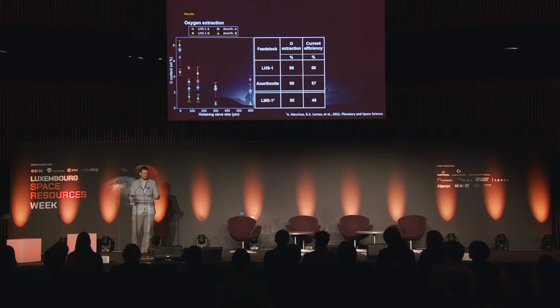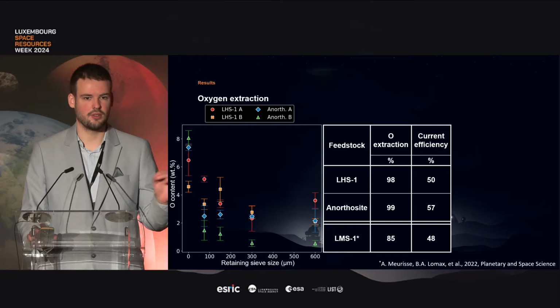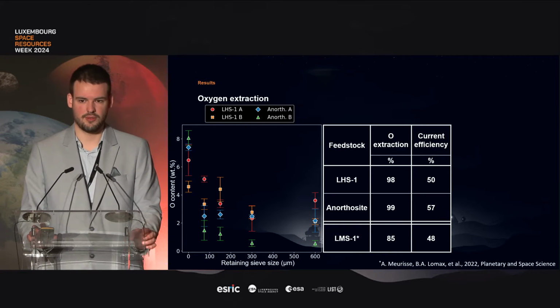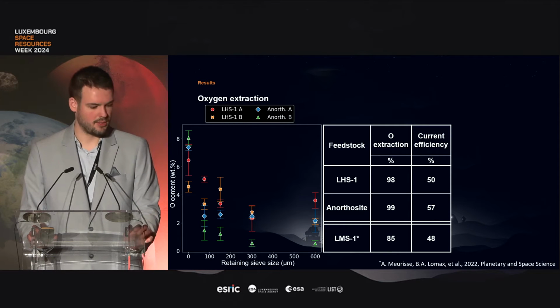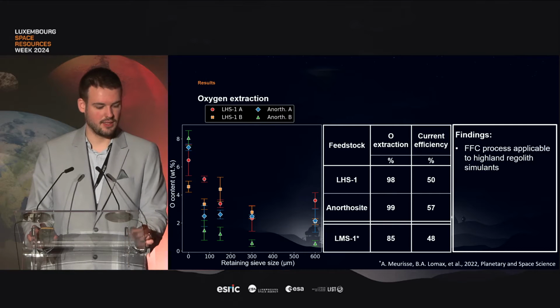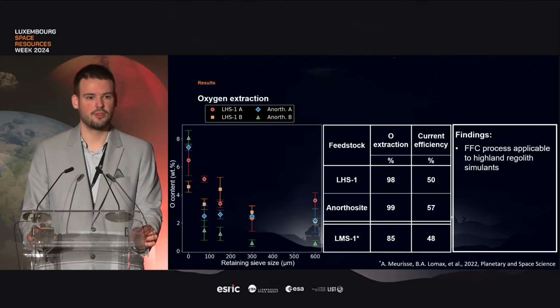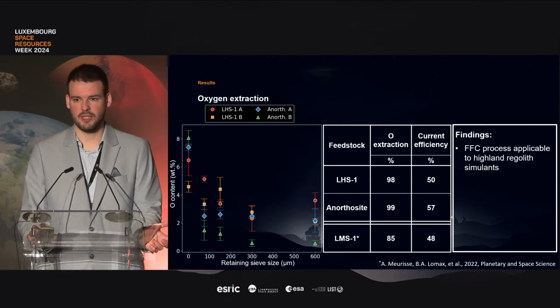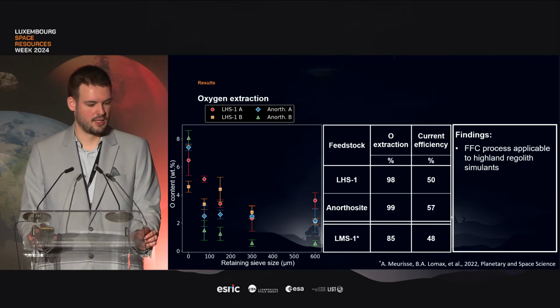And then, knowing the amount of current we passed during the electrolysis, we can also calculate the current efficiency. Having used a similar setup to what has been done in the literature, we can compare. There have been some changes, but the experimental parameters and the duration of the reduction are the same, so 24 hours. So over 24 hours, the first thing we can see is that the process is applicable to highland regolith simulants, which was expected, but it's always nice to confirm.